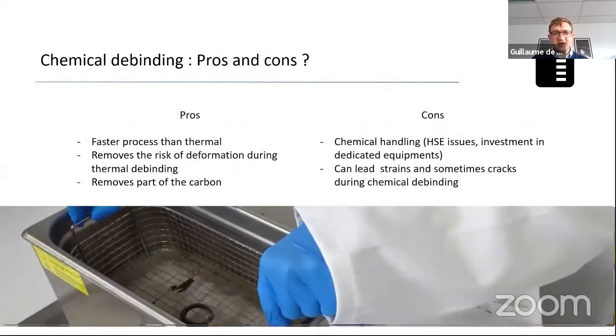So what are the pros? It's a faster process because you remove part of the binder before going in the furnace. It removes a bit the risk of deformation during thermal debinding, because once you have done the chemical debinding, there's not enough binder left so that the material could be soft. And that means you can ramp up a bit faster because you don't have that risk of deformation. And it also removes parts of the carbon, so that removes that problem of carbon contamination in the metal.